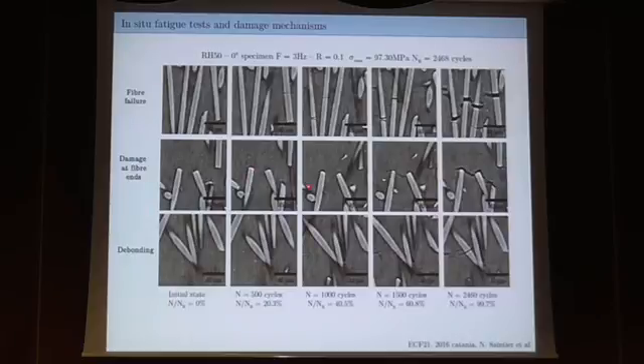So fiber ends damage, you can see it here quite clearly, and then it turns quickly, a bit more than the fatigue life, into small cracks. And these small cracks will join together to progressively create a micro crack. So this is the second type of damage.